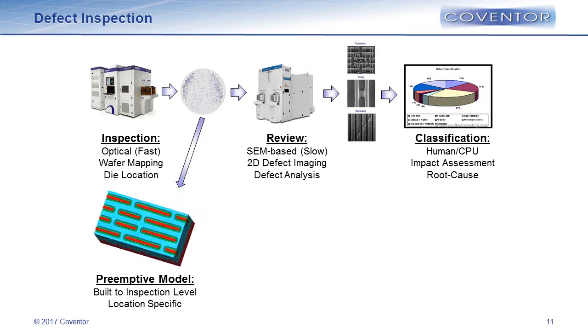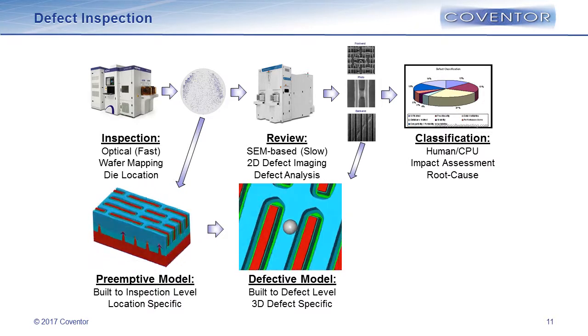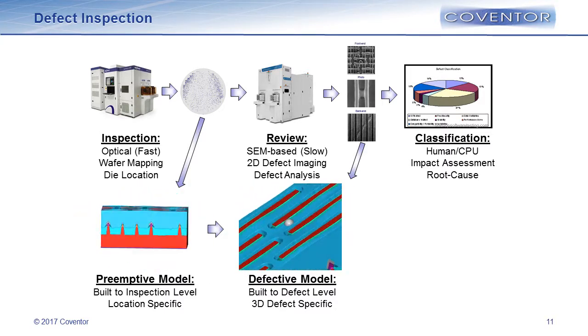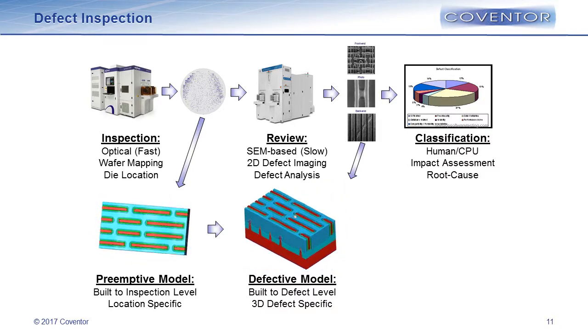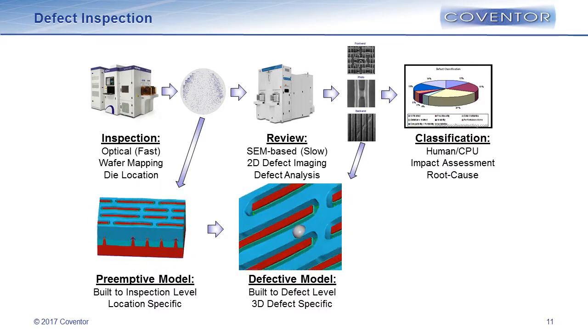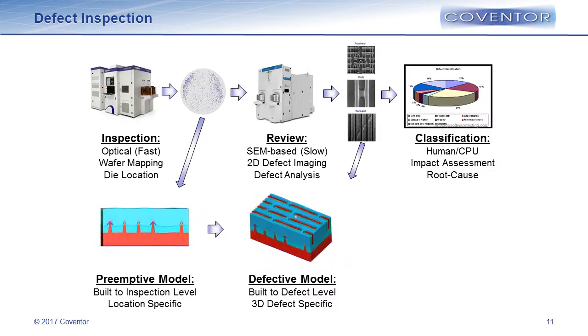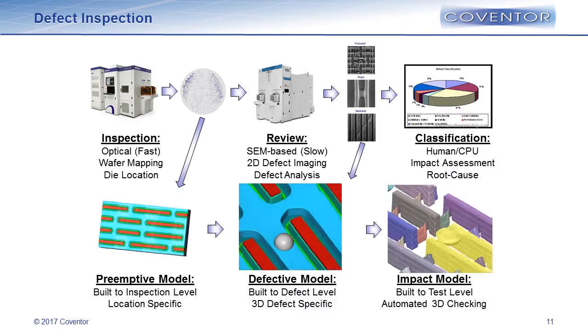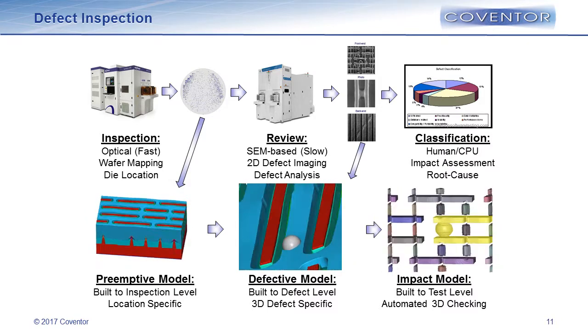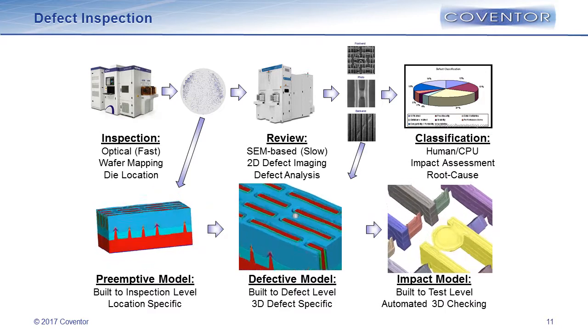At the point of SEM review, we can impart a defect in the appropriate location with the appropriate defect size and material — this is nearly instantaneous and can be done at the speed of wafers running through the fab. The models can then continue to run through the flow and we can do automated checking and analysis: this defect, if it's this material embedded at that depth, will cause a two-gate short — a hemispherical metallic short between two gates. Now we have automated electrical testing to classify this defect and its electrical impact. This is essentially taking the same process through the fab but applying virtual fabrication to highly educate engineers as to the real root cause of the defect and the impact at the electrical test level.